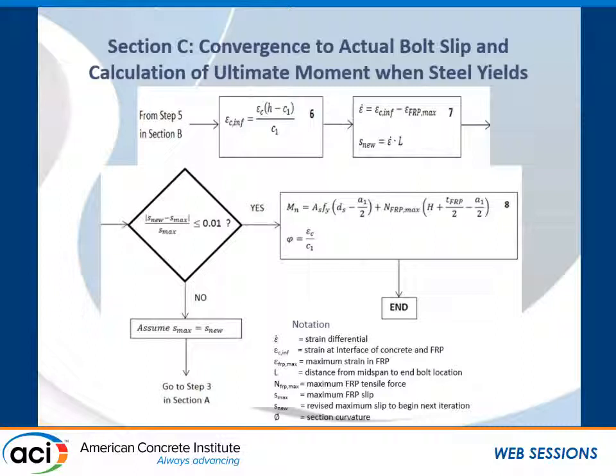At this point we compare that revised slip with the maximum slip from the iteration in question. If we are under our chosen limit of difference, and our chosen limit for this study was 1%, we've converged to a solution. If we are over it, then a new iteration is completed using the revised slip as the assumed maximum slip. Run another iteration. At the point that we've converged, the analysis proceeds to calculation of the ultimate nominal moment capacity and the section curvature. The equation shown here is for the situation where steel yields prior to concrete crushing.